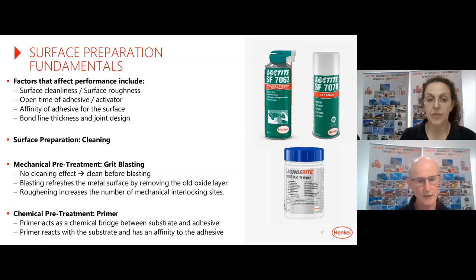Now, in terms of bond line thickness, typically, as a good rule of thumb, the thinner the bond line, the stronger the joint. But in some situations, a little fillet of adhesive outside the joint can help to dissipate the stress. So again, joint design is important and cleaning is important.